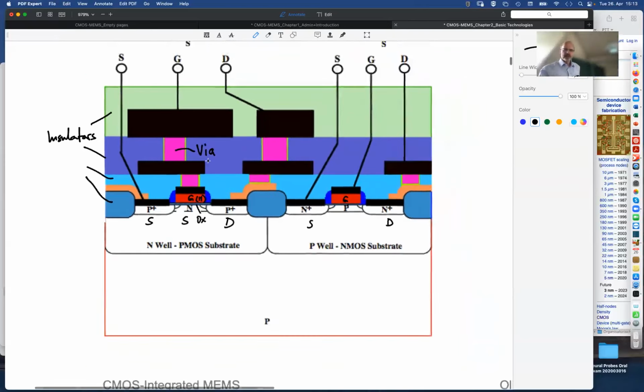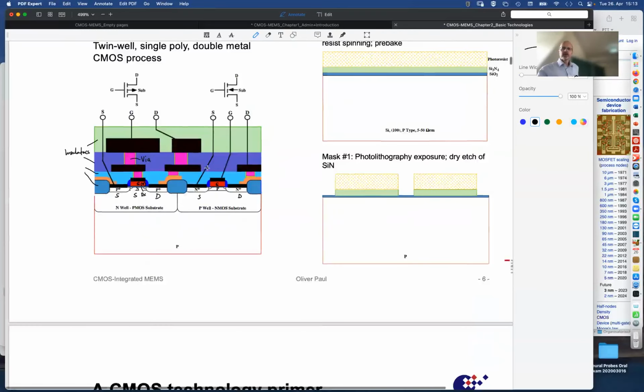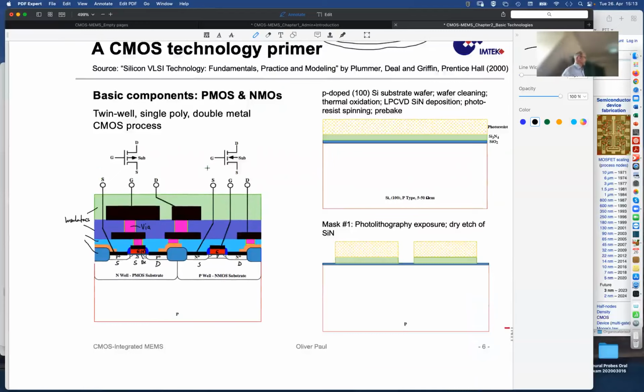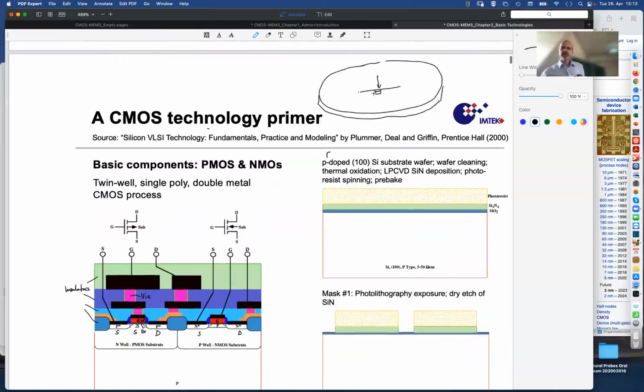And so now let's see how this is elaborated. So one starts with a silicon wafer with nothing on top, just bare silicon. The silicon is some 100 silicon substrate, which means that the crystalline directions in the silicon wafer, so the cubic crystal directions, are in such a way that one of the cubic axes is perpendicular to the wafer. And that means that the wafer has a certain arrangement of atoms on the surface, and this is what is usually taken for CMOS. This wafer is then cleaned, and then it is exposed to a thermal oxidation.